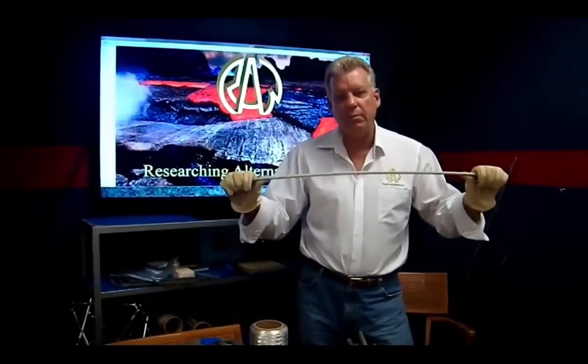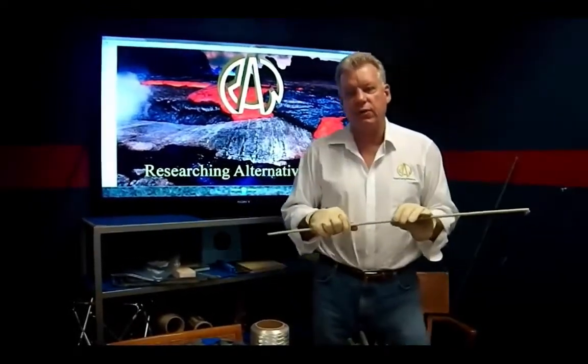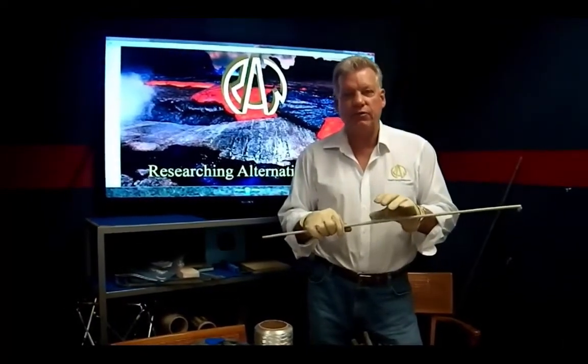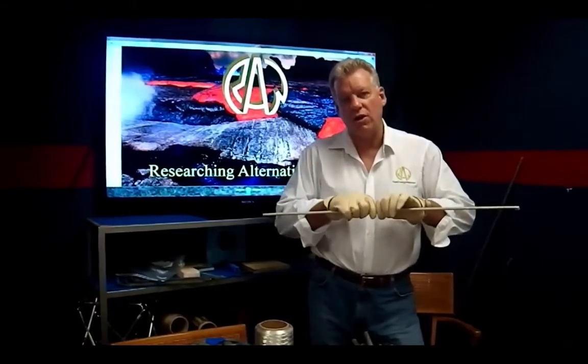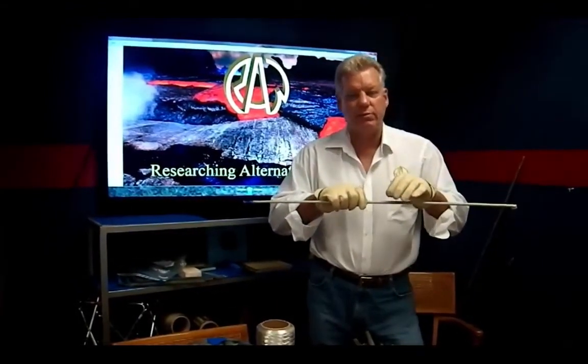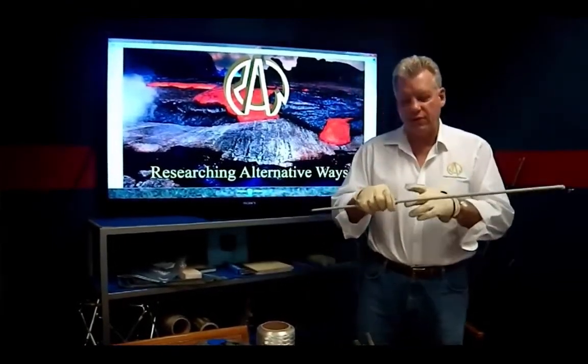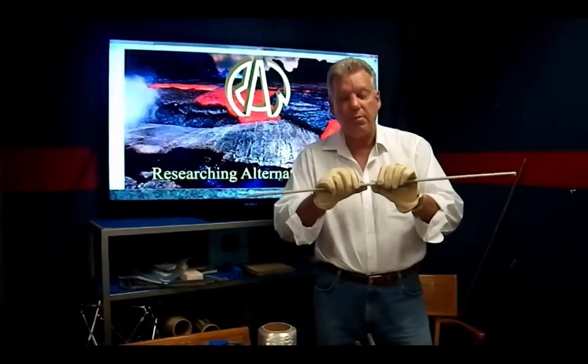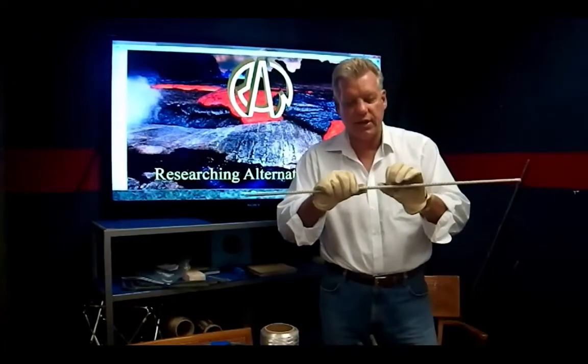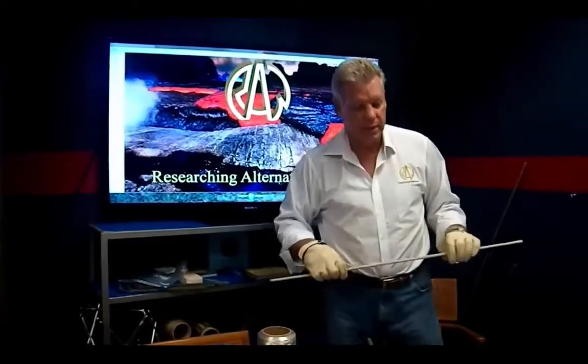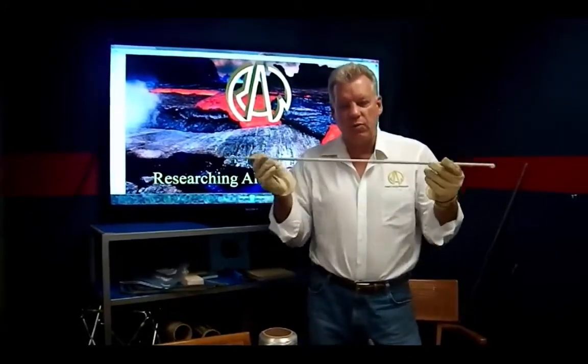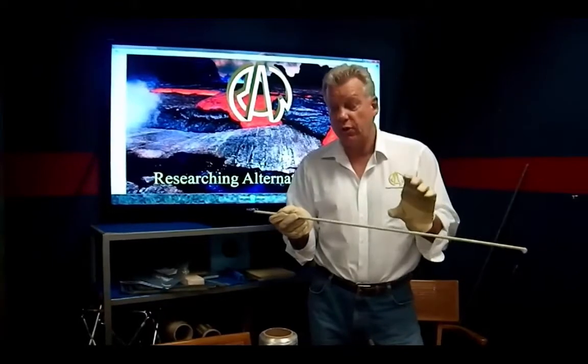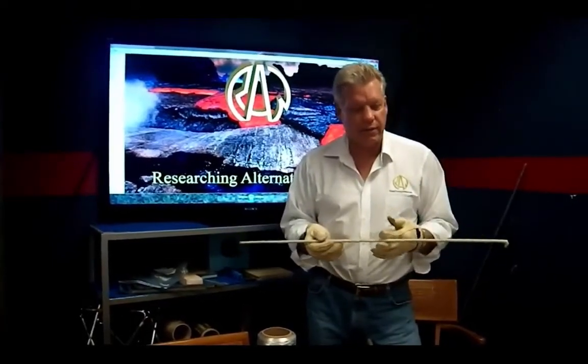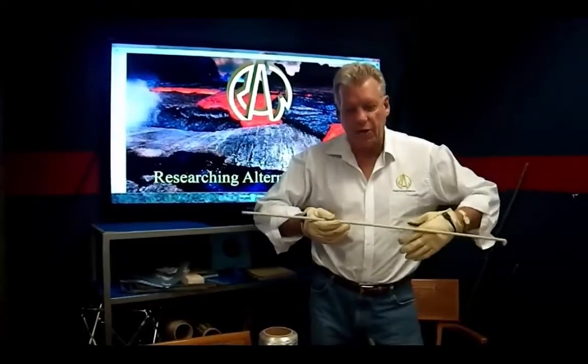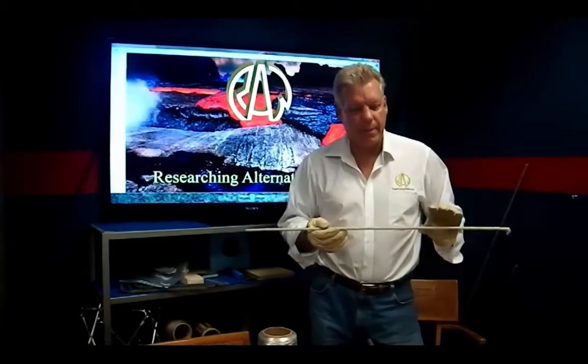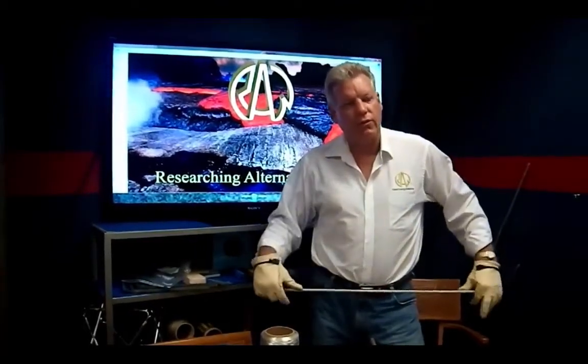It has a little bit of early bend and early stretch. And when you use fiberglass for composite or for concrete reinforcement, you have to be sure to use enough of it because it also has an elongation of about 4.7 to 5.7% elongation at break. That means for this diameter, it would actually stretch about, we'll call it 5% of the diameter before it parted or ruptured. So you're going to get a little bit of flex in the panel. If you move the material out closer to the surface of the panel, which you can do because it isn't going to rust the way that steel did, you get it further out on the bend moment and it stiffens the panel back up. The fiberglass is a little bit more brittle than basalt.